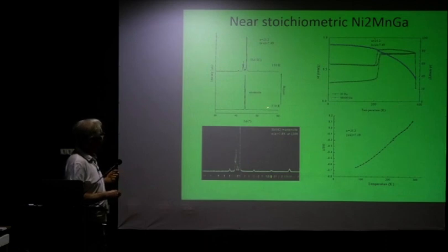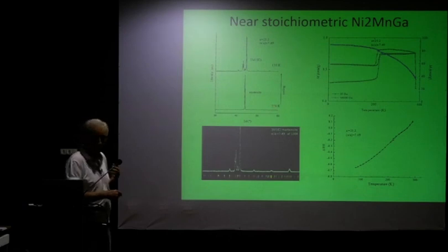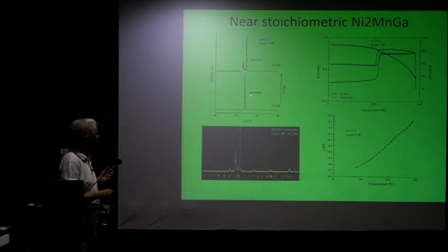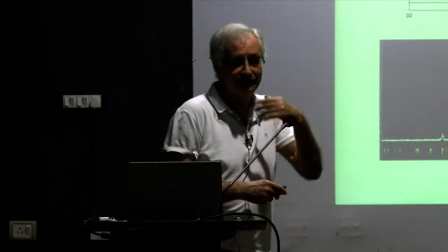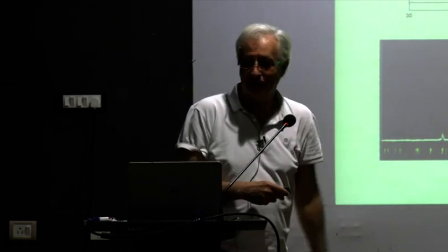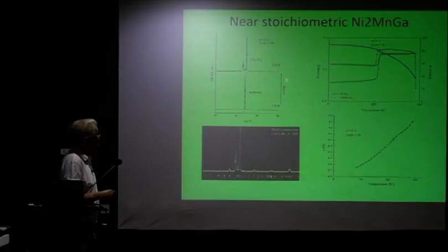So taking this example, we are here in an austenite state. So what you first do, you do your refinements. You see that you're in an austenite state, and then this here is identified as the 5M incommensurate state. Okay, you have the fourfold splitting. So you think it should be somewhere around 5. That's your starting point. That's how you start doing your refinements.